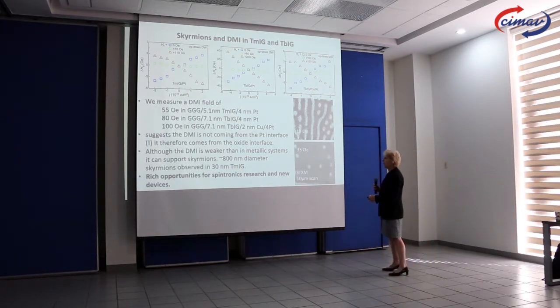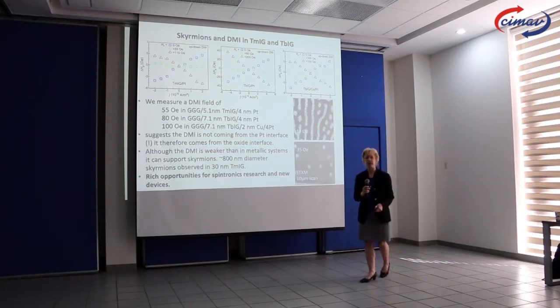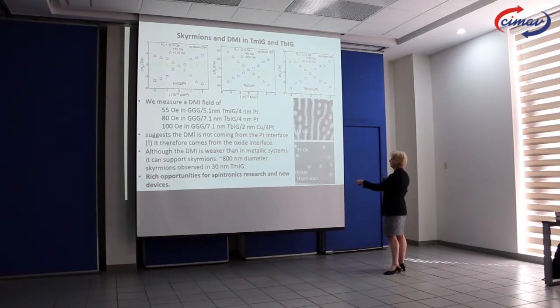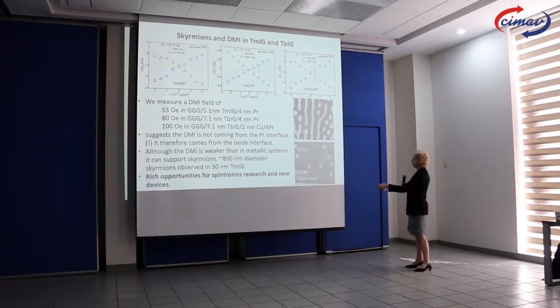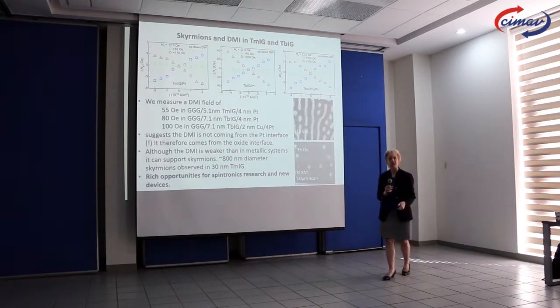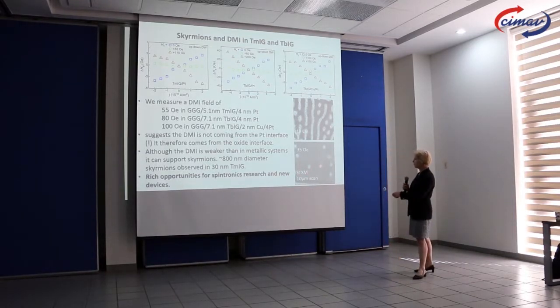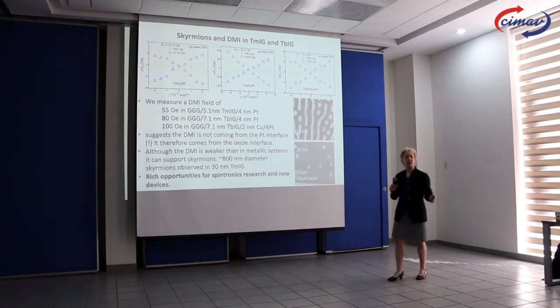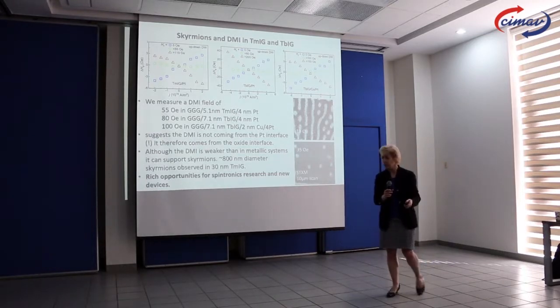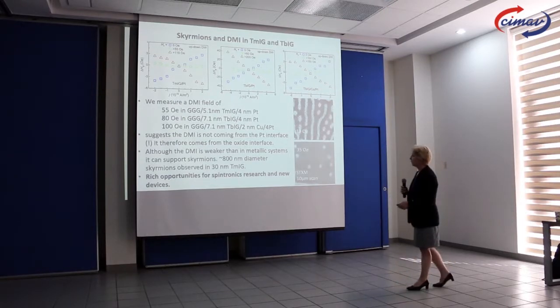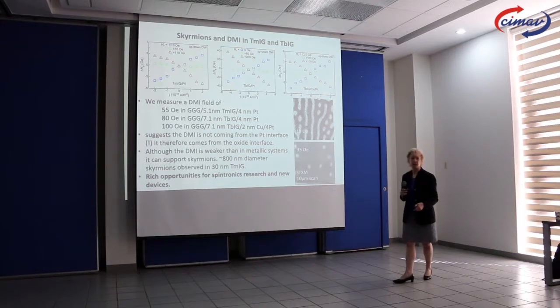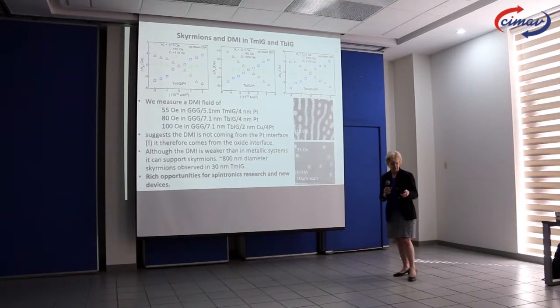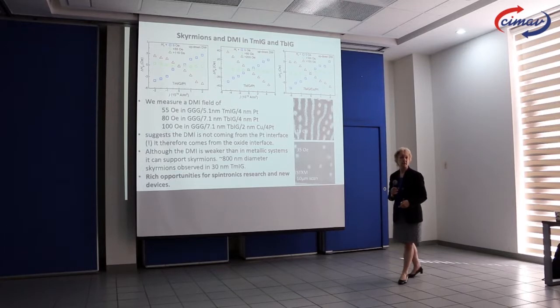One other thing is that DMI is essential to make skyrmions. So because we have a DMI which is fairly weak, it's still big enough to create skyrmions. And these are pictures of those little bubbles, those skyrmion bubbles, in thulium garnet, measured with STXM, which is a scanning transmission X-ray microscope. And these things are actually skyrmions. So now we can maybe think about making those skyrmion memory devices. Okay, so there's a lot of rich opportunities here for interesting physics and devices with these magnetic insulators.